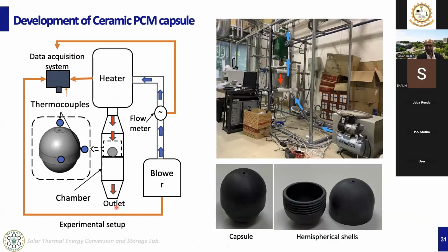And to increase the efficiency, we have been developing ceramic capsules as well. As you can see, in the previous project we used metal capsules. We had some structural stability issues, and some issues due to the corrosive behavior of the molten salt material on the metal parts, which is very corrosive. To avoid the corrosiveness, and at the same time to increase the efficiency and performance, we used a silicon carbide capsule. As you can see, we prepared two hemispherical shells, and then we joined them together to make a capsule like this.